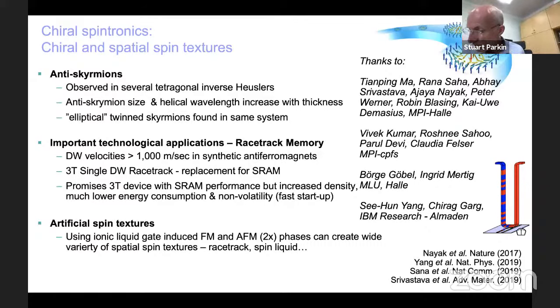So these antiferromagnets are super interesting because they have no net moment, but they can have a range of topological effects, if you like, including anomalous Hall effect, spin Hall effect, and other properties. And the presence of skyrmions? They have not been observed yet, but very likely. They haven't been observed yet because in an antiferromagnet, there's no net magnetization. So they're super difficult to observe. In principle they're there, but it's hard to see.